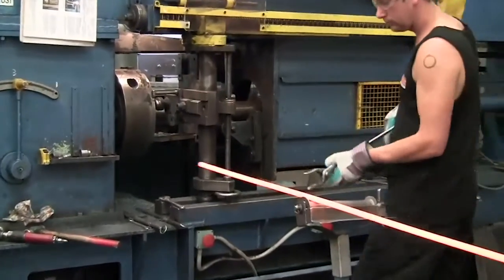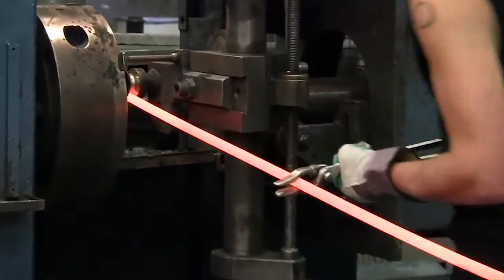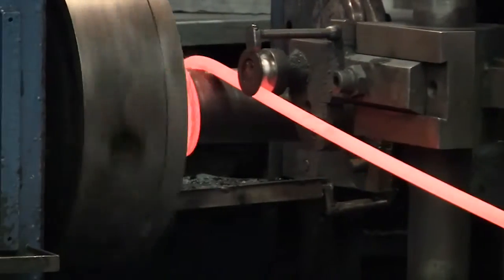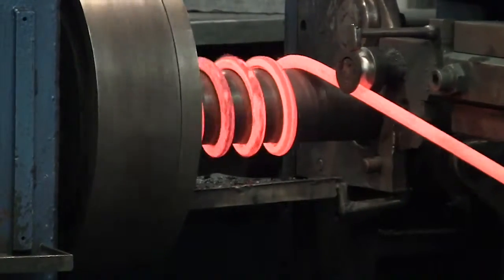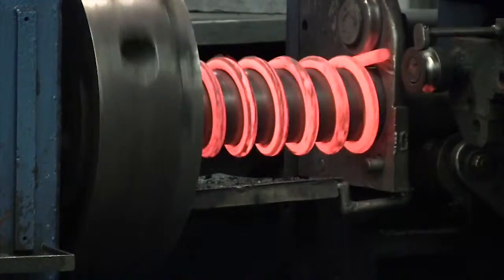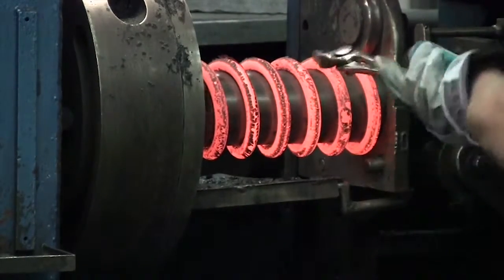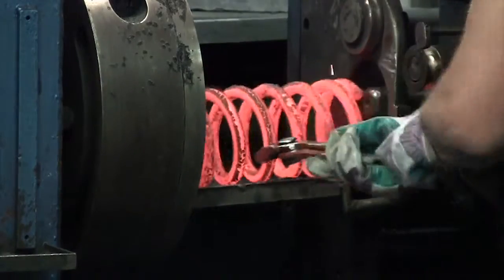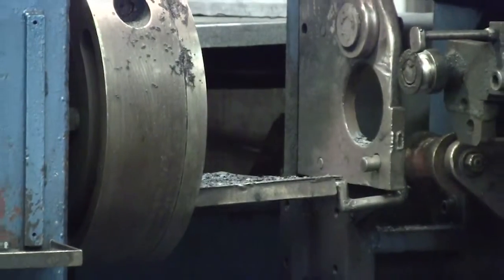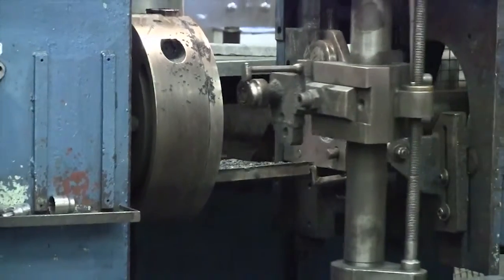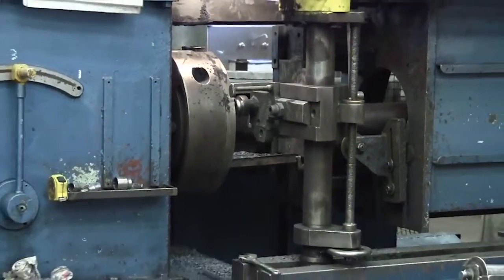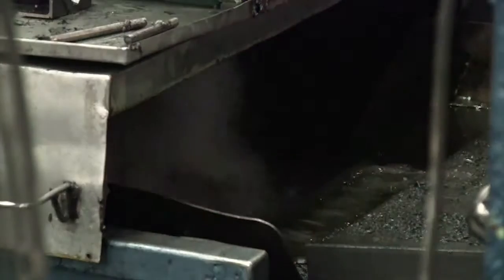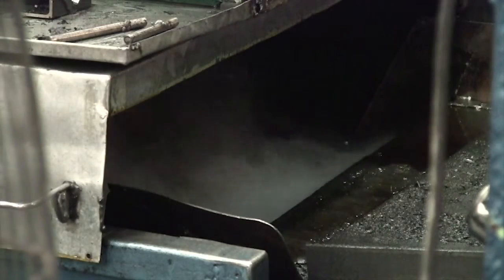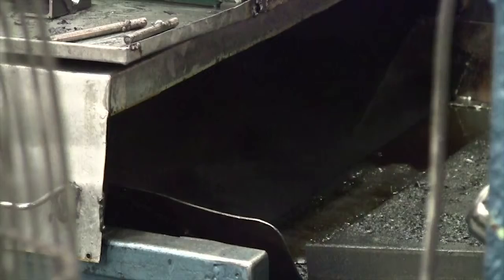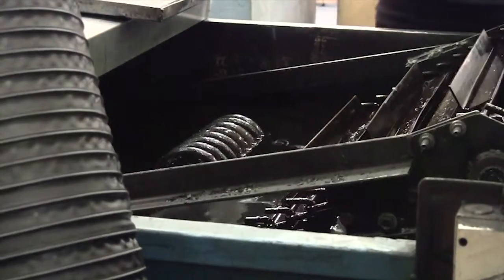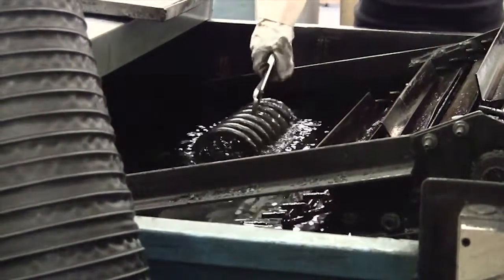After the exacting specified time, the bar is removed from the furnace and positioned into a fully computerised CNC coil winding machine. All coil springs manufactured by Pedders are hot wound, as this process is deemed to be more exacting. When the process has been completed, the mandrel withdraws and the coil is allowed to continue its journey to the quenching bath. The coils are then sent in convoy through an oil bath to complete the quenching process. The oil in the bath is maintained within its correct working temperature to maintain an even cooling progression.